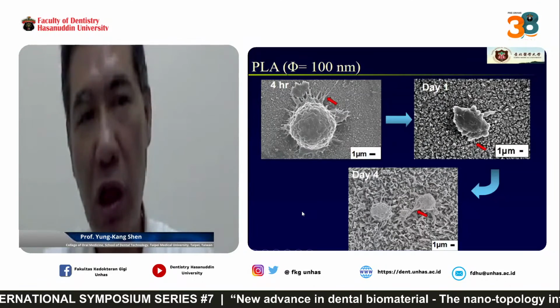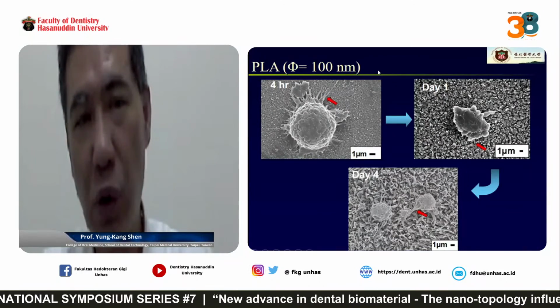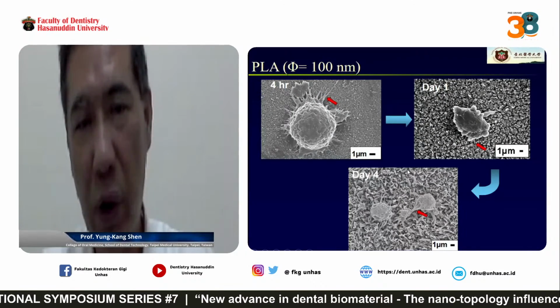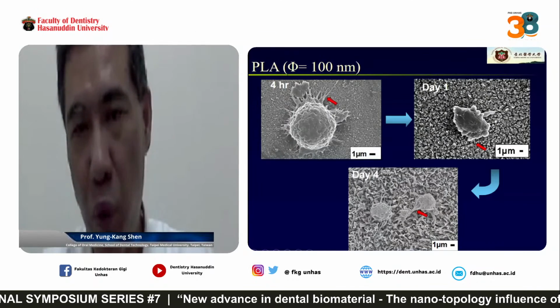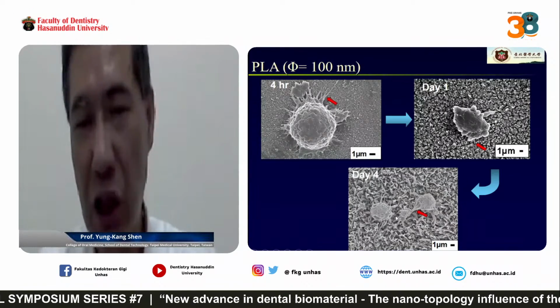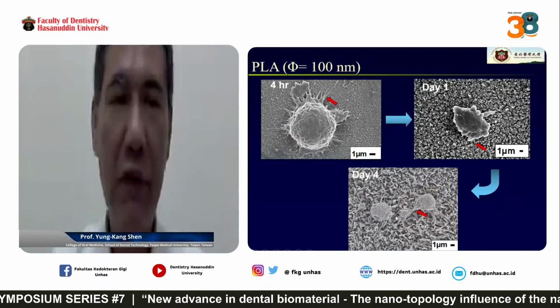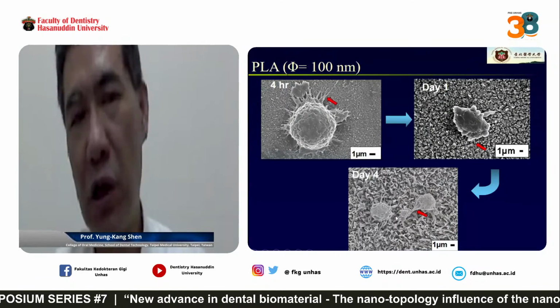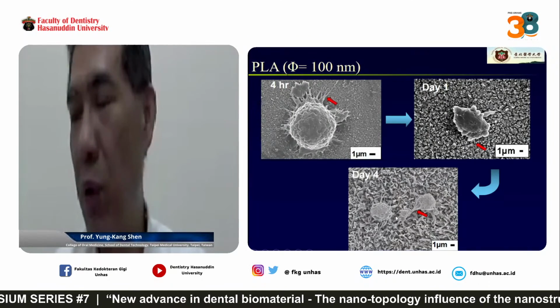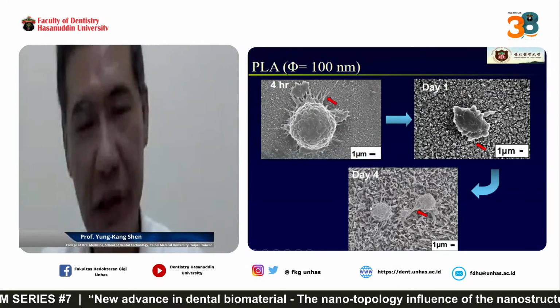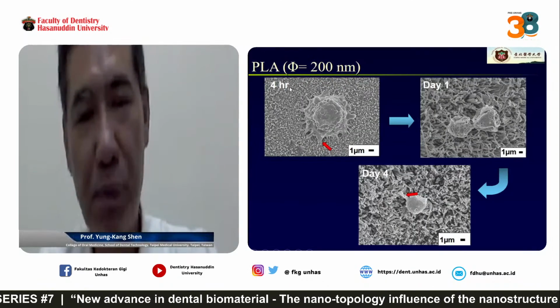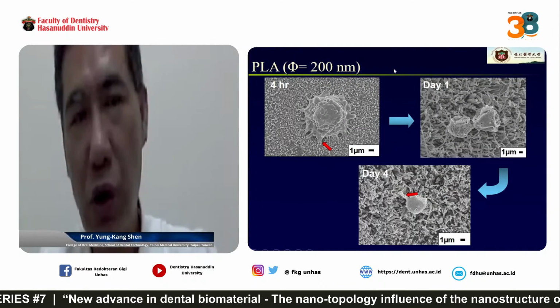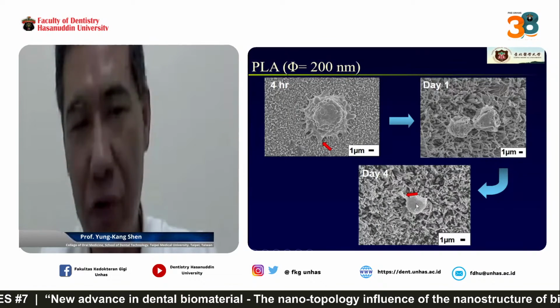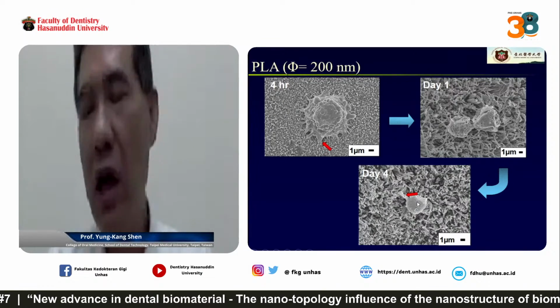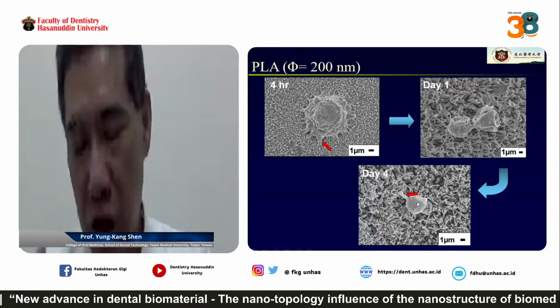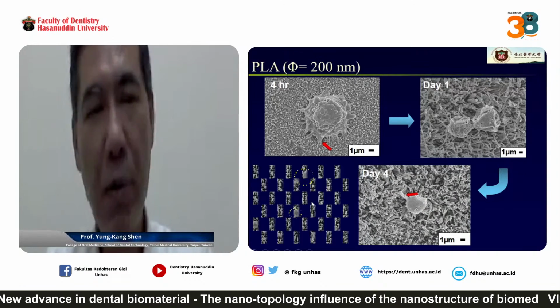This is PLA with nano pillar. The diameter is 100 nanometer. You can see 4 hours, day 1 and day 4. On day 4, one cell is divided into two cells. So you can see if you use the PLA with the diameter of 100 nanometer, you can get a very good cell culture here. This is PLA with a diameter of 200 nanometer, 4 hours, day 1 and day 4. Also, we can get very good cell spreading and good cell behavior here.